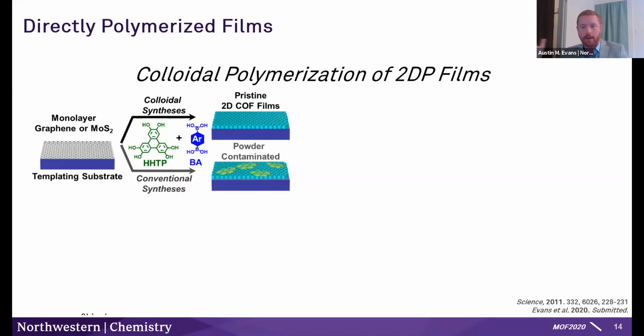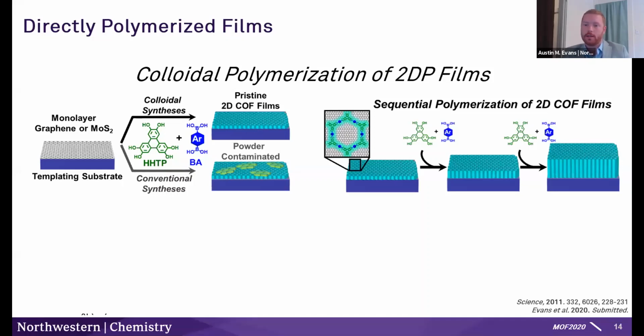But we realized, well, we have an approach now, a synthetic method, that's going to prevent that powder aggregation and that powder contamination on your film. And so we've been exploring using the colloidal syntheses to nucleate and then grow COF films directly onto these templating substrates. And because the films formed on these substrates are not contaminated, it's possible to do multi-series growth. So we can systematically increase the thickness of these materials. And that's reminiscent of the growth strategy we used before, and is really powerful as a design strategy to get films of appropriate thicknesses for different types of devices, which is always an important parameter.